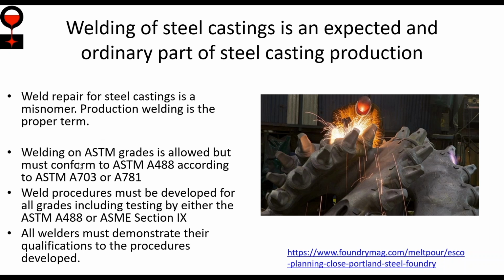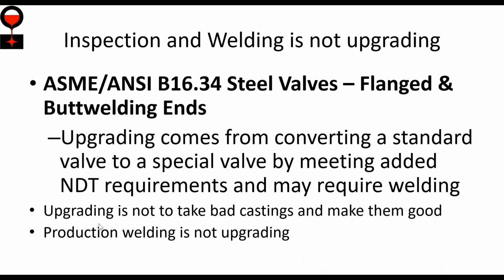We not only qualify ourselves to ASTM A488, but we also can qualify to ASME Section 9, to the boiler and pressure vessel code. So if I'm qualified to Section 9, that counts for ASTM A488. But I have to prove that I have a weld procedure that meets the mechanical property requirements, and that my welders who are actually doing the job are capable of meeting the quality standards.